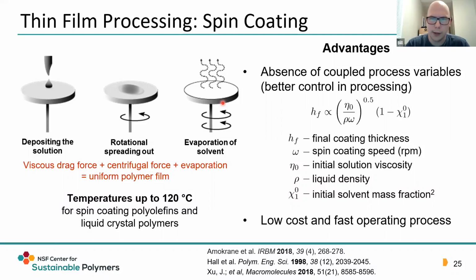What's helpful about this is that it's pretty easy to tune the height of your film from some independent variables based on your solution's viscosity and how fast you're rotating. One of the unique capabilities we have here is to do high temperature spin coating, which allows us to make polyolefin films or liquid crystal polymer thin films as well.